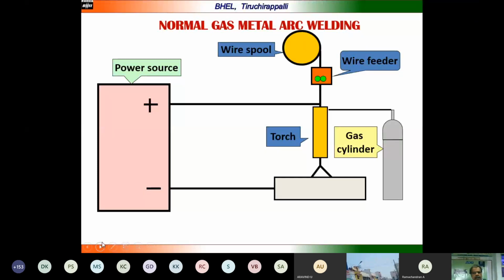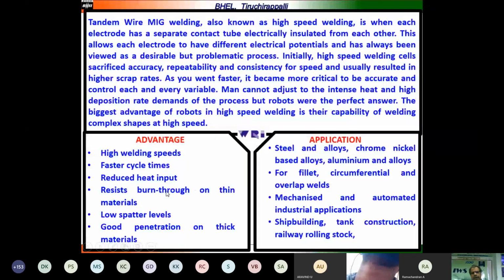advantages are high welding speeds can be achieved, faster cycle time, reducing heat input, resistance to burn through on thin material, low spatter levels, good penetration on thick material, steel and alloys, chrome nickel based alloys, and aluminum alloys can be welded easily. Fillet and circumferential overlaps can be done, mechanized and automated easily for industrial application. Shipbuilding, tank construction, and railway rolling stock are the industries where it can be applied very easily.